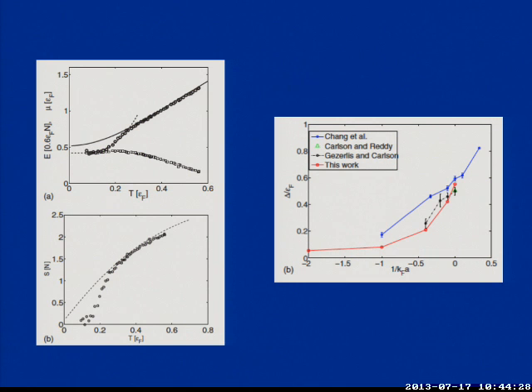We calculated the entropy as a function of temperature, and also extrapolated later on the pairing gap at zero temperature as a function of the inverse scattering length. So these are our results. These are Carlson and Reddy. Sanjay sits there, you see, and there are all the results, but they did this calculation with GFMC, so they work directly at zero temperature. We work at finite temperature, extrapolated, and obtained that, well, basically you agree with them.